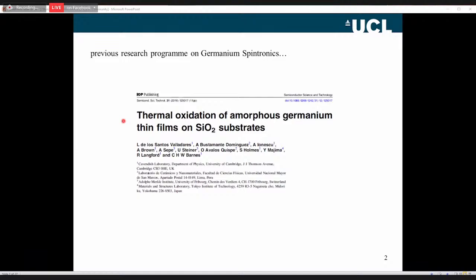From amorphous, we made the germanium crystalline and polycrystal, unfortunately not monocrystal. Then unfortunately it also oxidizes and also diffuses. There is a diffusion of germanium into silicon, and there is a reaction between germanium and the germanium oxide. It's quite tricky to work with germanium in that case, the crystallization. However, in order to avoid all these problems, Stuart Holmes has grown this by MBE, right? With molecular beam epitaxy, grown with big chambers and so on.